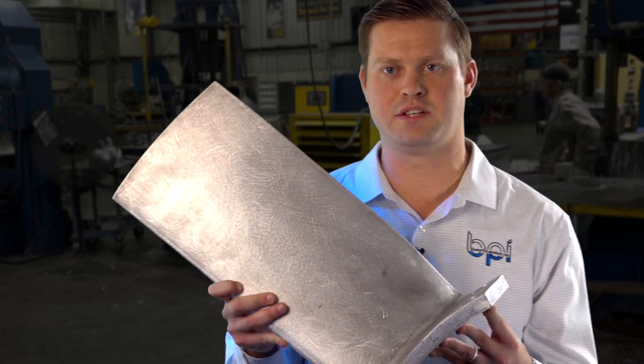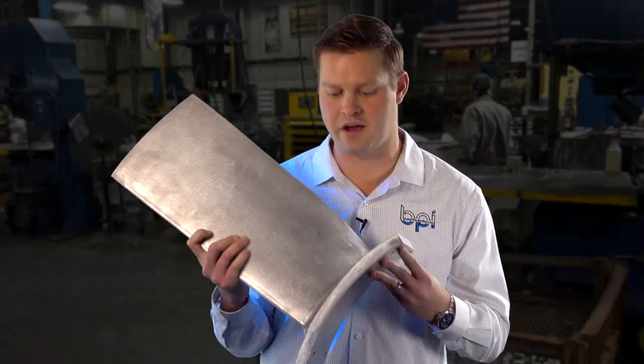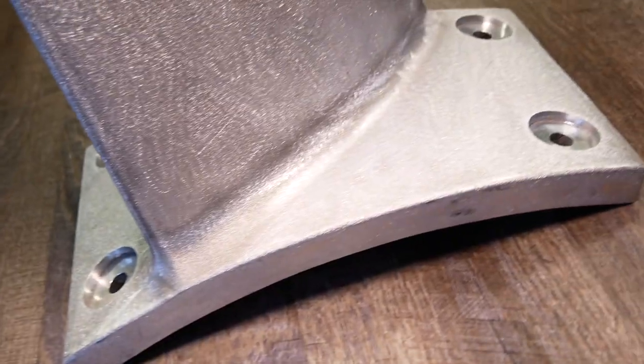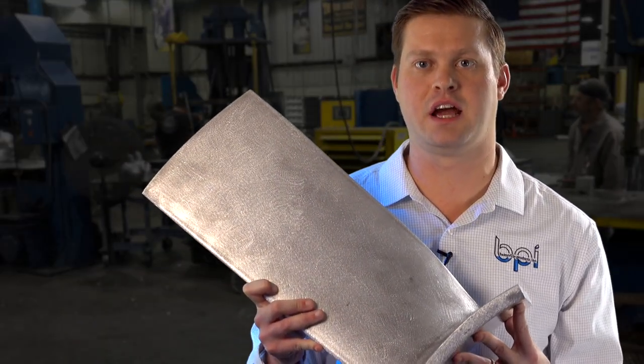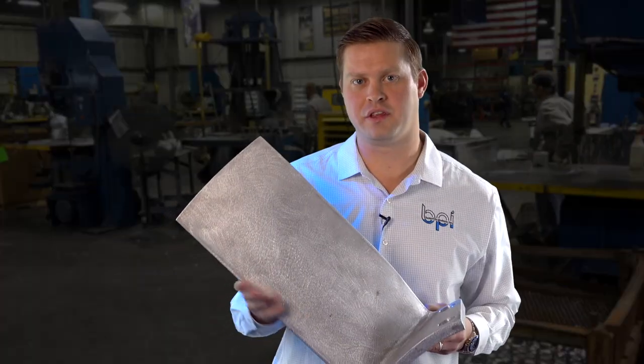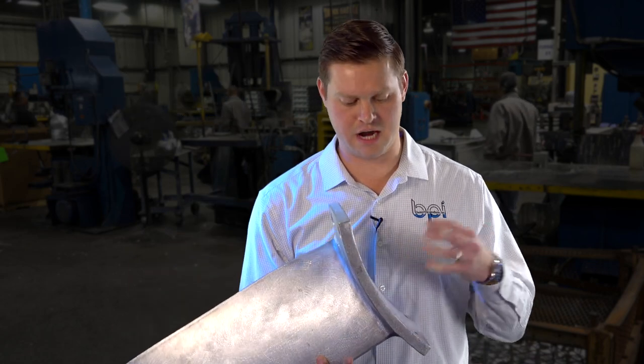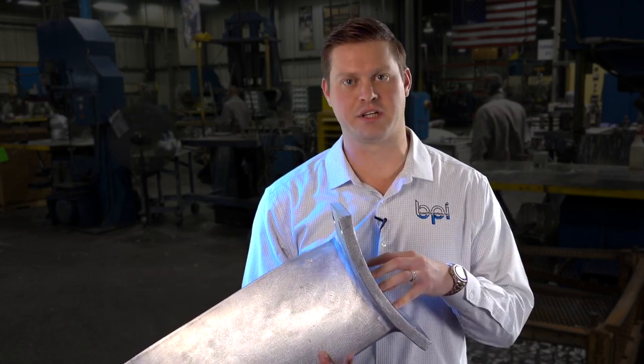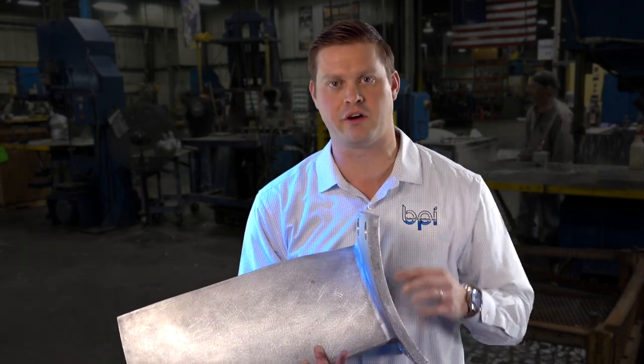Picture this piece on a 72-inch fan on a locomotive. The customer came to us with issues — hairline cracks at the bottom of the base. This was originally being cast using a sand casting process, and the issue was they were casting it from the tip. What Batesville Products did was flip it upside down, feeding the metal through the thick section, really eliminating the turbulence that was creating the hairline cracks.